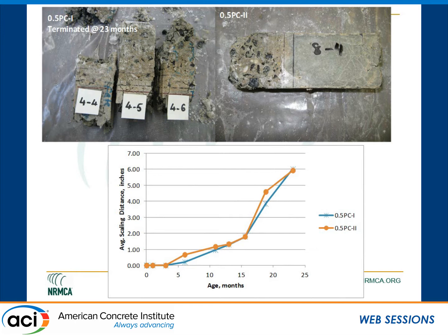The scaling distance for Type 1 and Type 2 is almost identical at the exposed surface. So we're not getting the benefit of a different cement type when it comes to physical salt attack. It's a more physical type of failure rather than a chemical one, and we understood that phenomenon. This is quite different compared to chemical sulfate attack.